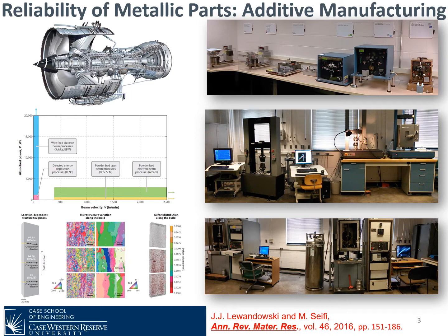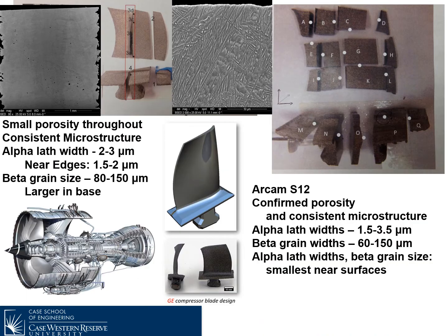And so in this case, the example on the bottom left is a tall build of titanium 6 aluminum 4 vanadium. It's 100 millimeters tall. And what we see is significant property variation along the length of the build. We also see from tomography on that same exact sample significant differences in the defect density. And more detail, also differences of the microstructure as you go from the bottom to the top of the build. And so in these cases, these were evaluated in our test laboratories, and we were looking at the mechanical reliability. In that case, you could imagine us doing similar things on projects that may be of interest to you.